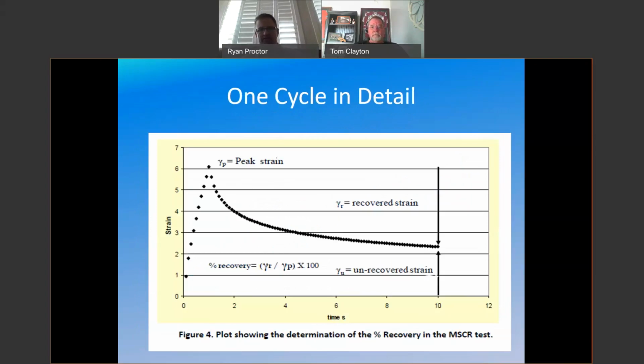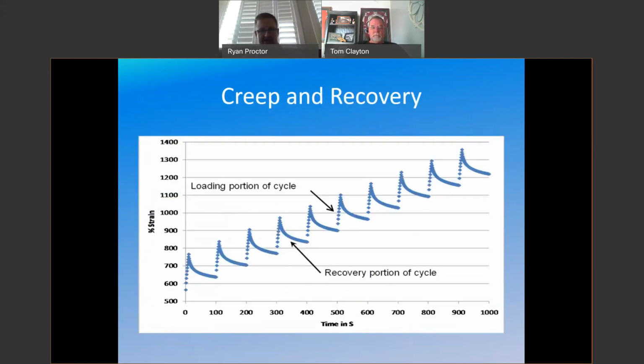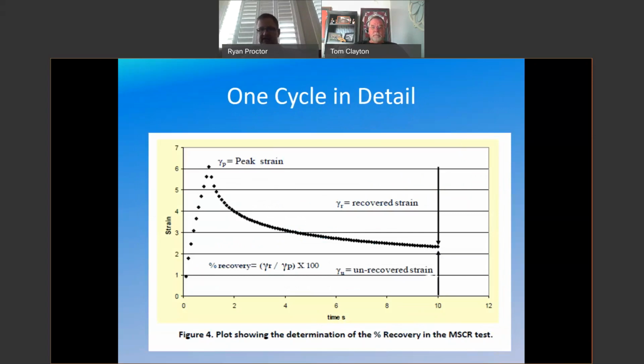We also look at peak strain, and that's the highest value that you get, kind of like a toughness from that toughness and tenacity test. So this test uses existing equipment, which is good, and you try to combine some of the facets of some of those SHRP plus specs. There was a movement for a while to replace some of the DSR tests with this.